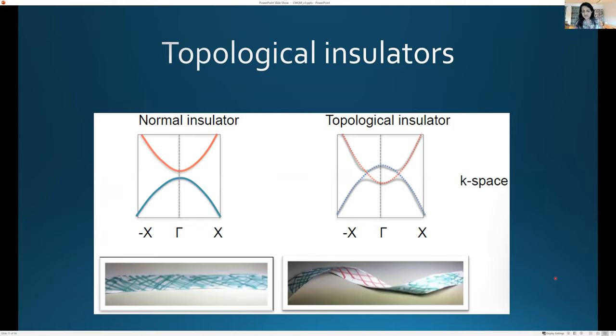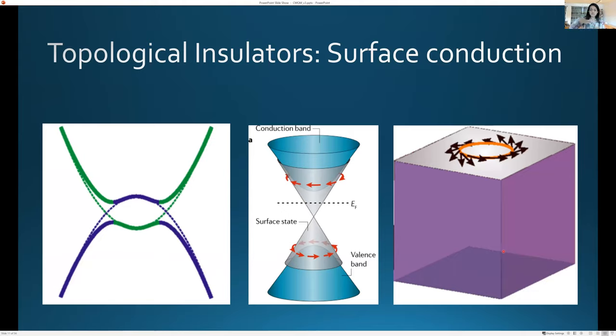And just very briefly, without going into much detail, the signature of a topological insulator is that one has a special kind of gap, which has to do with hybridization, however, to do with spin up and spin down bands, in which case the result is that only the surface of the material is conducting, whereas the bulk of the material is insulating. And so this is another category of insulators that has come into prominence much more recently, but samarium hexaboride is unique in being a correlated example hypothesized for such a topological insulator, which is why we started studying this material, because we wanted to see if we could see the Fermi surface associated with this conducting surface.